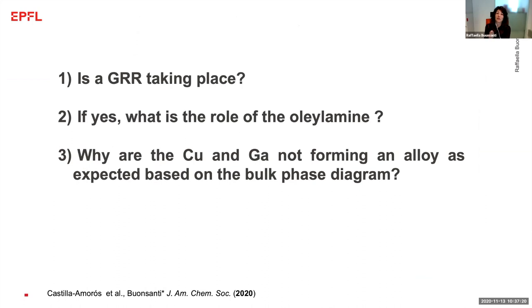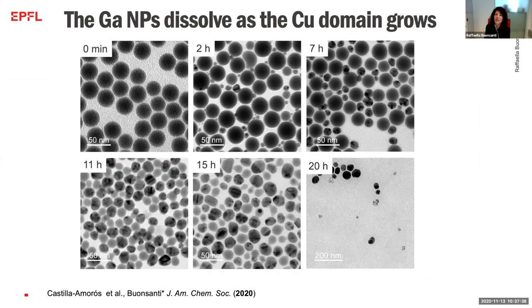So at this point, we wanted to understand: first of all, is a galvanic replacement reaction taking place? If it is, then what is the role of the oleylamine? Because oleylamine is normally used as a reducing agent during the synthesis of nanocrystals. And why are they not forming an alloy? So Laia started answering these questions. First of all, she took time aliquots and saw that the gallium domain becomes smaller and smaller. It also shrinks and deforms as the copper is growing. So the gallium dissolves as the copper grows, which is really consistent with the galvanic replacement reaction.